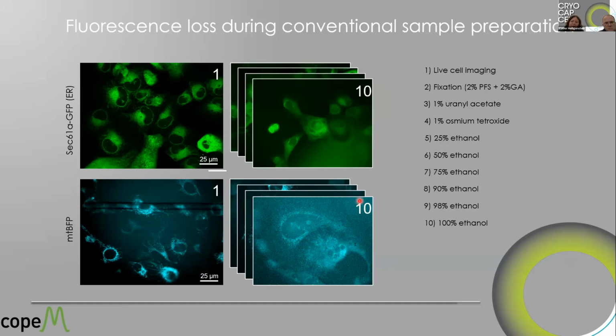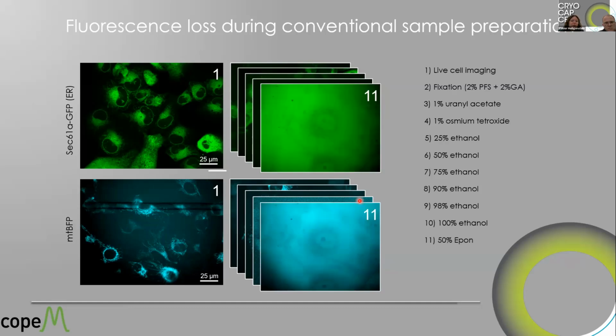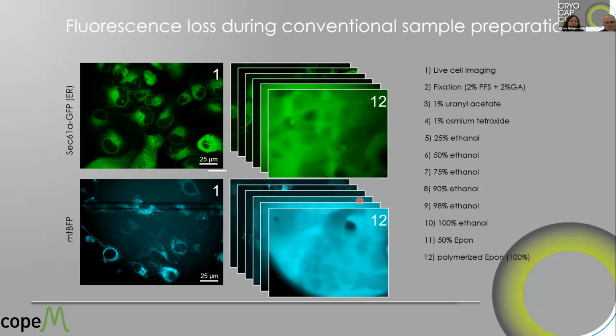But this goes back to what Wanda Kukulski and Susan Nixon also said. If you don't fully dehydrate the sample during freeze substitution and keep a little bit of water, you will maintain the fluorescence. And this is now the epoxy resin, and you see there we have all the fluorescence of the epoxy. And yes, it doesn't get nicer.